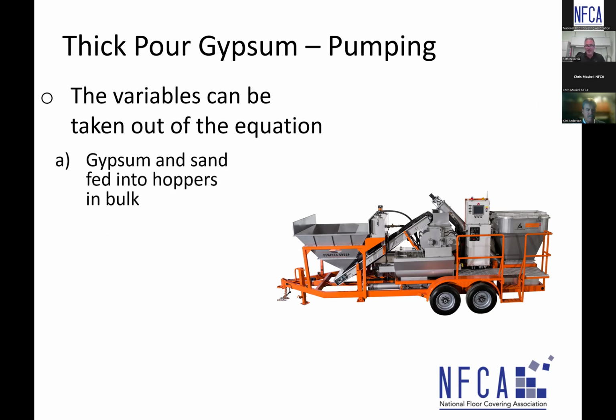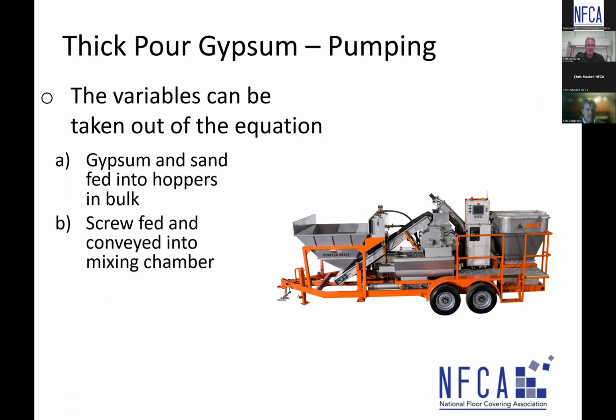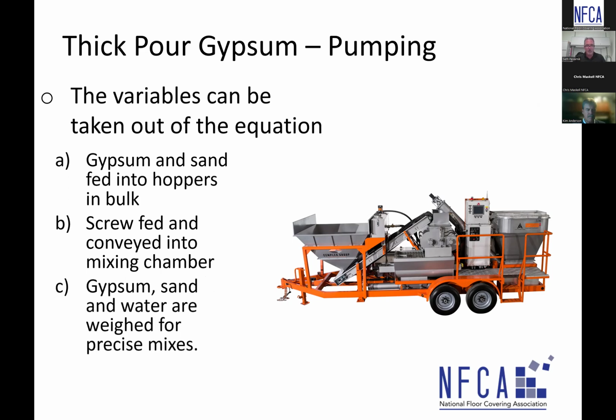So the gypsum and sand are fed into hoppers in bulk. They're screw fed and conveyed into the mixing chamber to get the right amount of gypsum and sand. And then the water is weighed as well as a part of this whole pump process to give a very specific water amount, so that we achieve the right amount of those constituents and have a material that is in very good integrity.